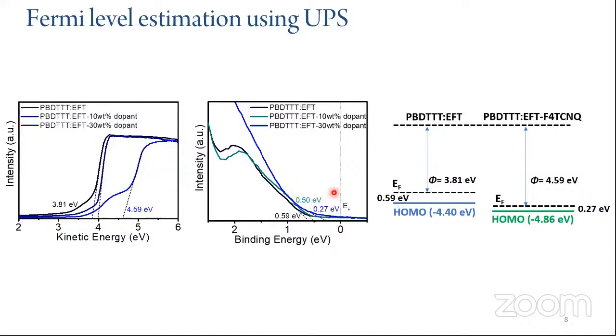And this is further confirmed by the Fermi energy spectra, that is upon doping, we can see the shift decrease from 0.59 electron volt, that is E HOMO minus E Fermi, to 0.27 electron volt. And we have formulated this band energy diagram with the work function as well as the Fermi energy values.